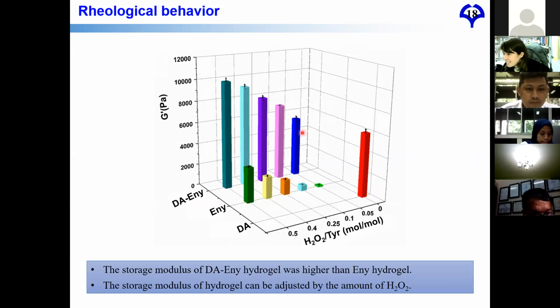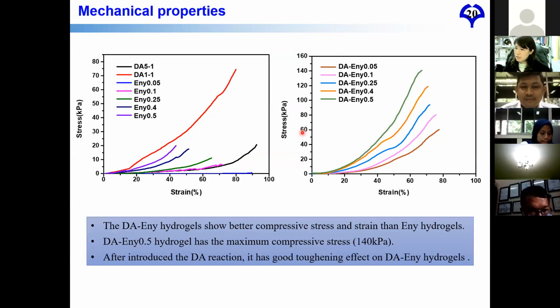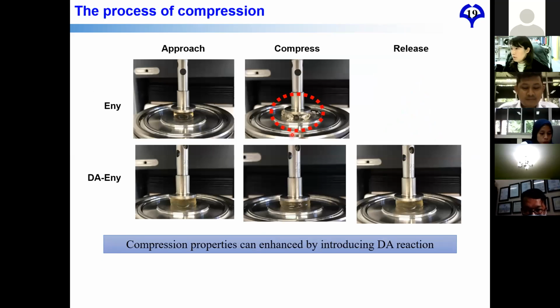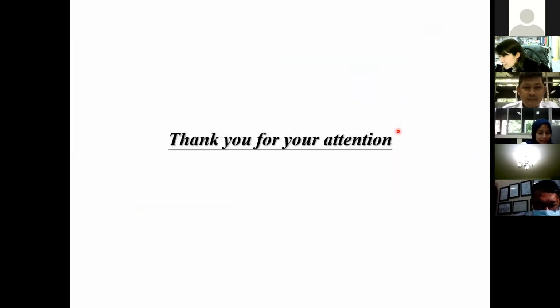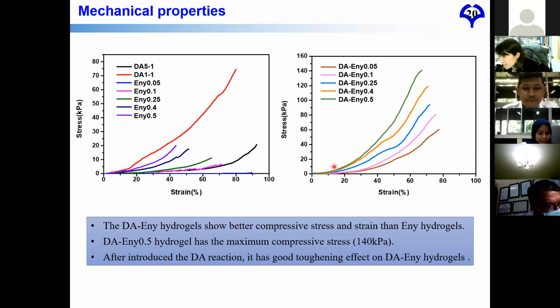And this one is very important, because with only enzyme, the hydrogel may be very weak, so during the compression test, it will be broken. But if we introduce the Diels-Alder reaction, you can see that the hydrogel will be very strong. During compression, it will not be broken, and we can also keep the shape of the hydrogel.